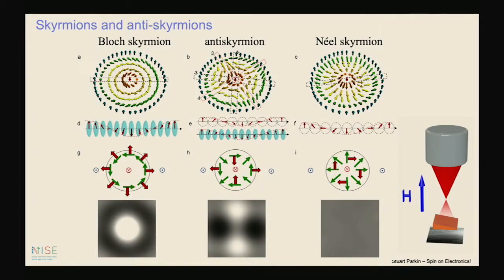So in the middle, we can actually use micromagnetic simulations to include exchange, anisotropy, and the Dzyaloshinskii-Moriya exchange, anisotropy, dipole fields. And we can calculate these respective structures. And then we can calculate what we expect to see in the Lorentz microscope, depending upon the focus of the electron beam with respect to the plane of the sample. This is shown here. On the right-hand side, you actually see nothing if you look at a Néel skyrmion, because the electron beam is displaced around the circumference of the object, so there's no change.